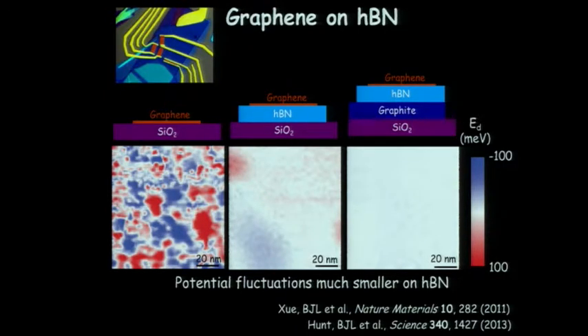And what you see here is essentially a white display, which has basically reached the noise level of our measurement. So have you checked, when you use graphite gates, have you found a correlation whether the HBN is thicker or not? Because there's some evidence lately coming up from basically thick HBN. You don't need graphite underneath. It gives you everything that you want, which is just be far away from the.